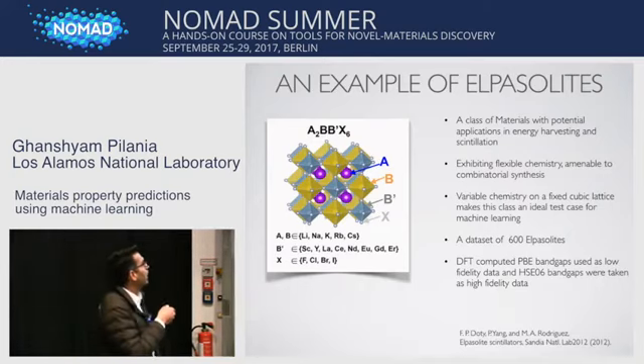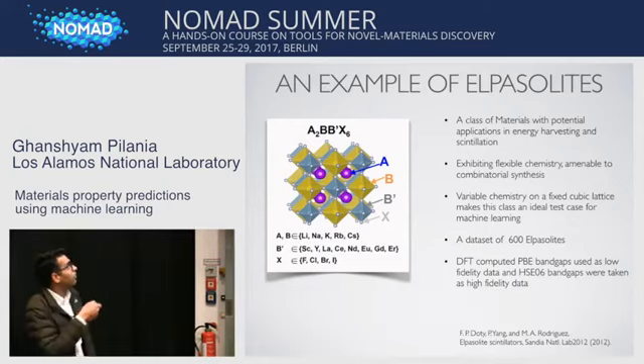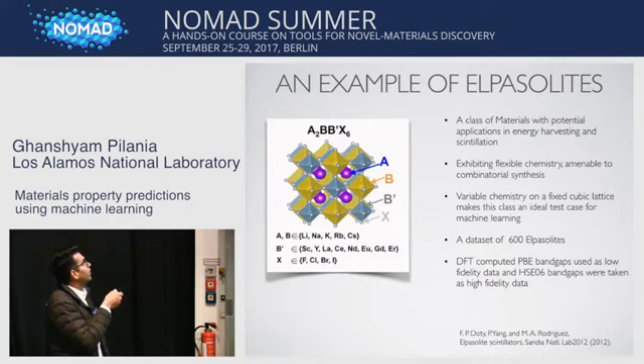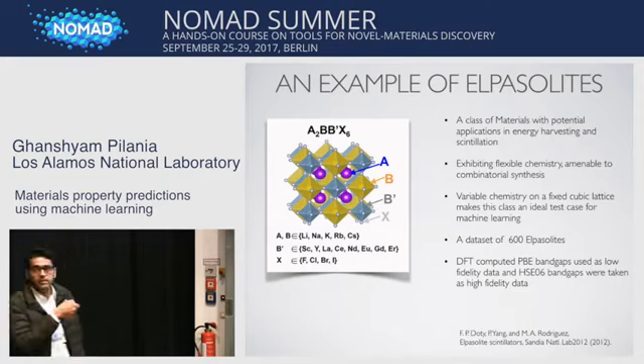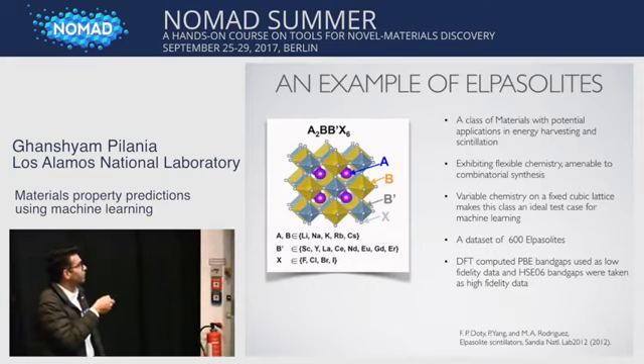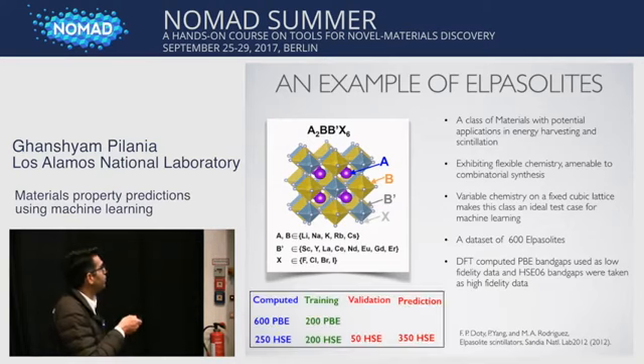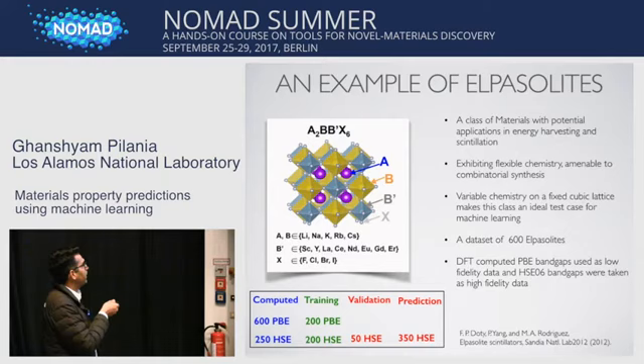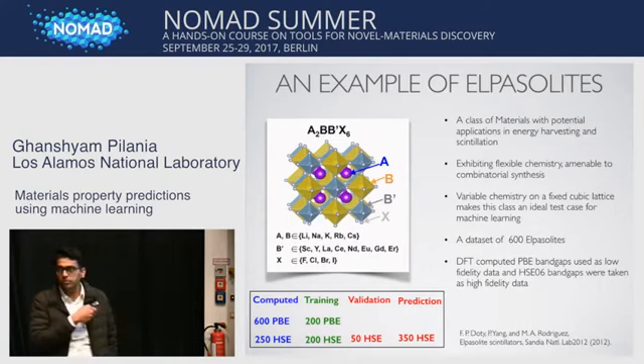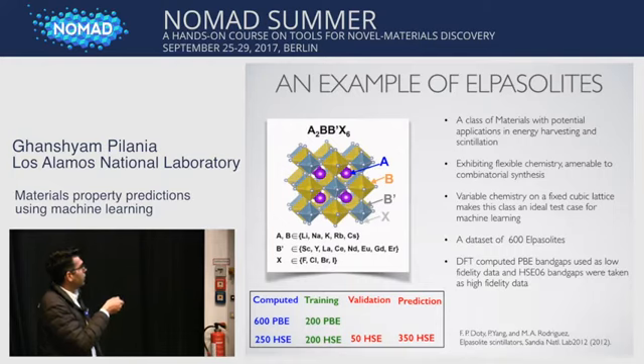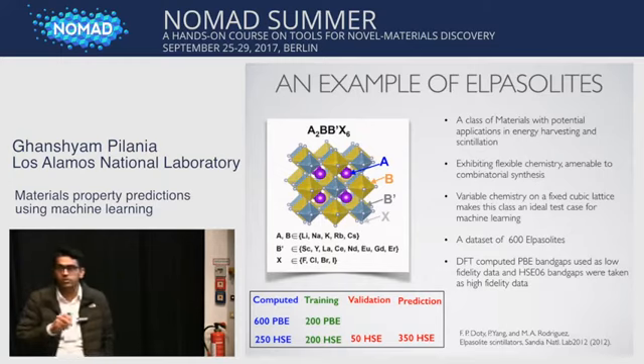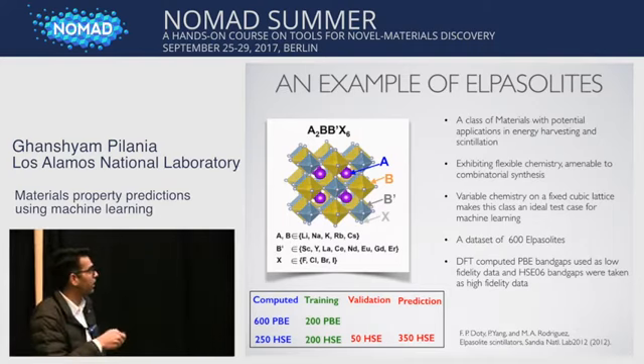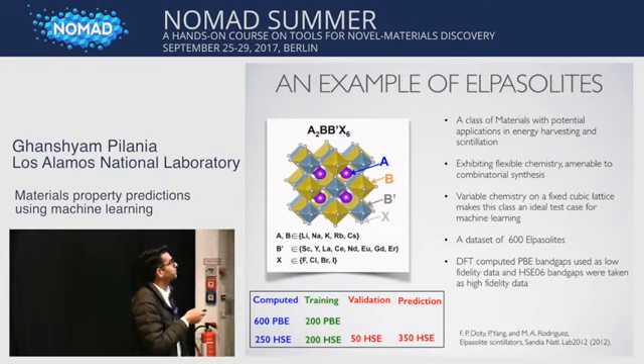And for materials, we take halide double perovskites of A2BB'X6 type, where elemental species at A, B, B', and X are shown here. In this data set, we have about 600 or so compounds, and we compute PBE band gaps for all of them. And then we take a random subset of 250 compounds and compute HSE band gaps for these. And then we take 200 PBE and 200 HSE data points and use them in the training. And the remaining 50 HSE data points are not touched during the process of training and are only used for testing. And predictions are made on the rest of the data set.